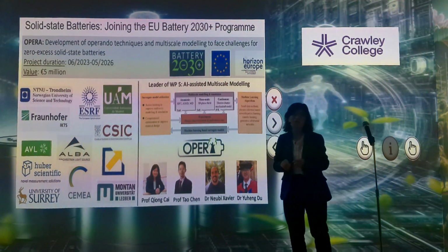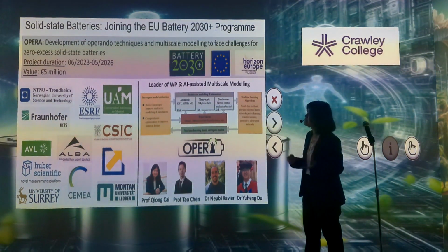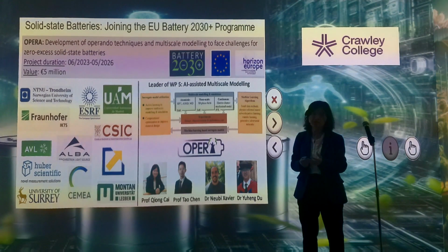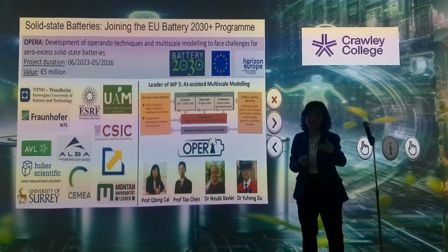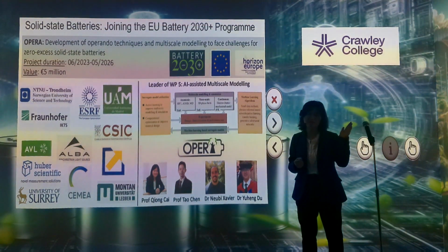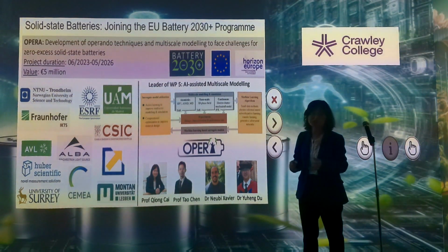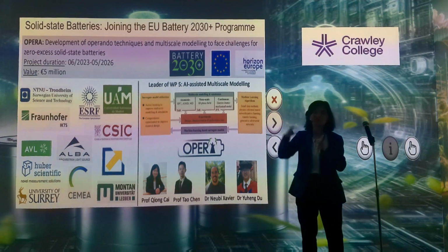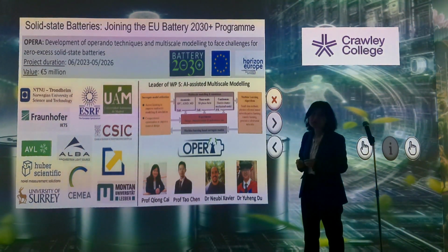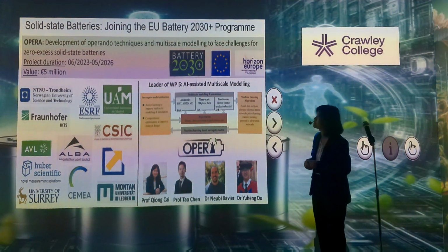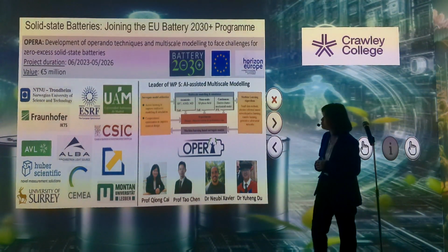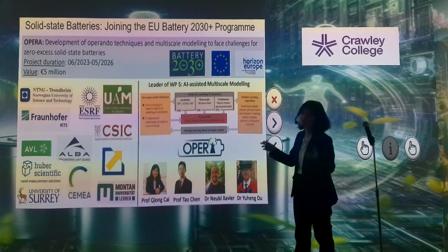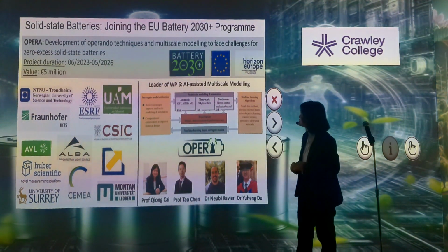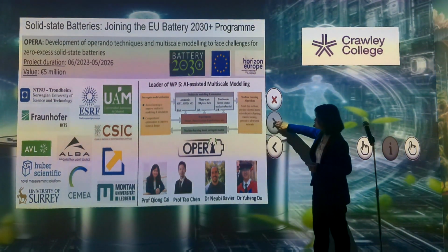Within this Horizon Europe funded project, we're developing solid-state batteries without lithium metal at the fabrication stage. And that will make the fabrication process much easier because, as I said just now, lithium metal is very sensitive to air, and so the fabrication process will be much simpler, and also the energy density would be much higher. But there are still technical challenges, so within this consortium, we work with another 11 partners across Europe to tackle the technical challenges, and our task is to use computational modeling to help select the best interlayer material that can enable very stable battery performance.